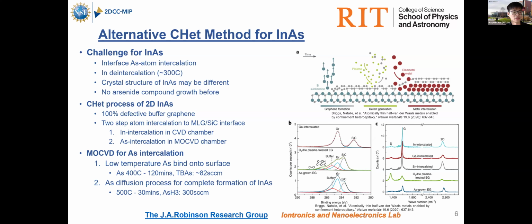However, that brings us another issue, which is that indium tends to deintercalate, usually at about 300 degrees Celsius. While this happens, it makes this two-step growth even harder, because as we do plasma treatment, intercalate indium, and then do plasma treatment again and then arsenic intercalation, during this process we might lose some indium atoms due to this deintercalation effect. Therefore, we need to find a solution to this, especially since no arsenide compound was grown with CHet before.